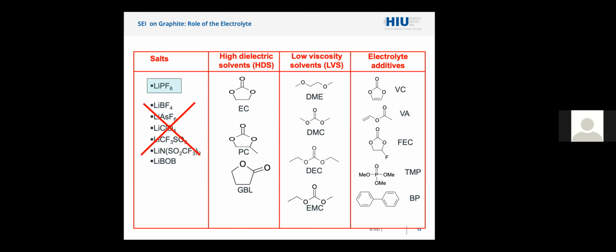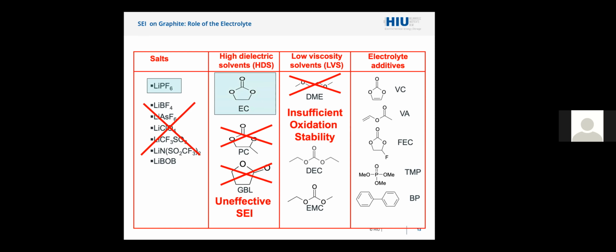Okay, but for example, TFSI is commonly used as an additive also in these electrolytes. And regarding the high dielectric constant solvent, EC is the preferred one because PC and GBL do not really form effective SEIs. For the low viscosity solvent, usually DEC and EMC are selected, and then there is a multitude of electrolyte additives. I'm just listing a few here, but actually there are many more, and these are very confidential, which are also added.